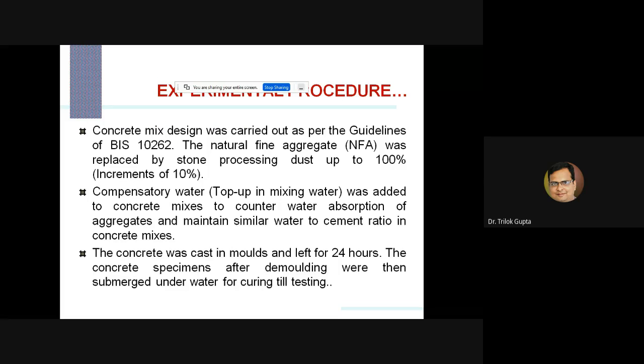Now the concrete mix design was carried out as per the guidelines of IS 10262, and we replaced the natural fine aggregate by stone processing dust in increments of 10%, going up to 100%. As from the last table, the water absorption of the stone processing dust was around 4 times that of the natural river sand. So that's why we maintained a similar water cement ratio. In the study we used a 0.45 water cement ratio. We used compensatory water, meaning a top up in the mixing water was added to the concrete mix to counter the water absorption of the aggregates, so that the same water cement ratio could be maintained. Casting was done as per standard practice. We cast the molds, left them for 24 hours, then submerged them in water till testing.